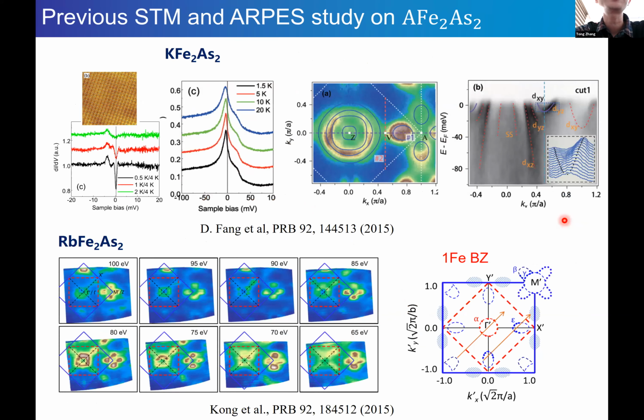Now this page shows the previous STM and ARPES study. Compared with the heavily or optimally doped iron-based superconductors or parent compounds, the study in this kind of 1-2-2 hole-doped system is, I think, still limited. So the previous STM only focused on the potassium 1-2-2, and they observed density of states peaks around the Fermi level and a small superconducting gap. And the ARPES study shows that there are three hole-like pockets at the center of the Brillouin zone.